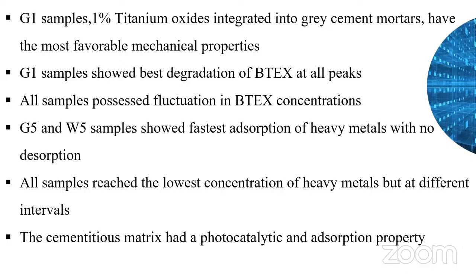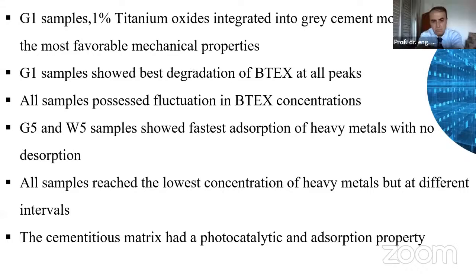Now, there are some recommendations for further study. We noticed an interesting fact that the matrix itself, the cementitious matrix itself, has an impact on the removal of some contaminants, and this is to be further studied, and also understanding the reasons behind the production of byproducts which are causing an increase of the absorption of BTEX.